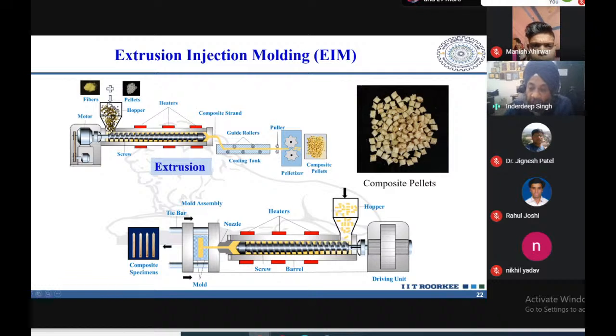So these are the composite pellets that you see on your screen. This pellet now has both the fibers and the polymer, and these pellets are then used as a raw material in the injection molding machine, as you can see here. Now in the previous process we were talking about direct injection molding. We can put direct fibers and polymers, a batch of fiber and polymer, into the hopper, and then we directly inject it to get the samples.